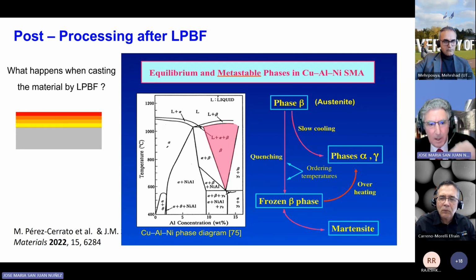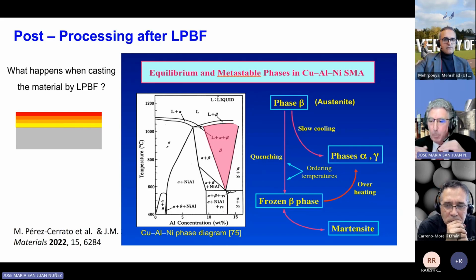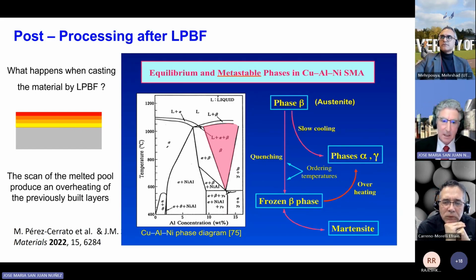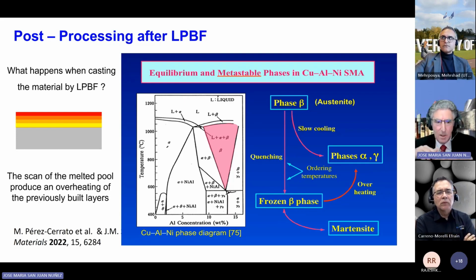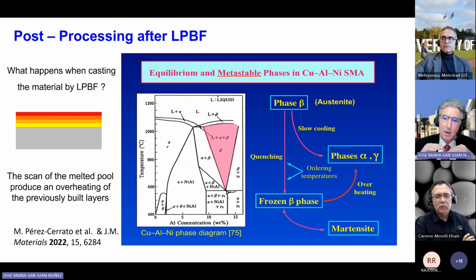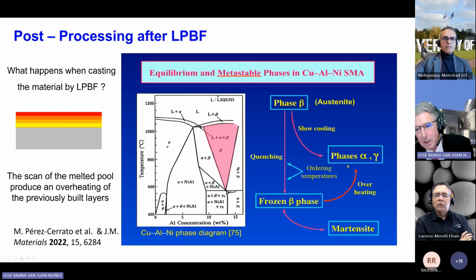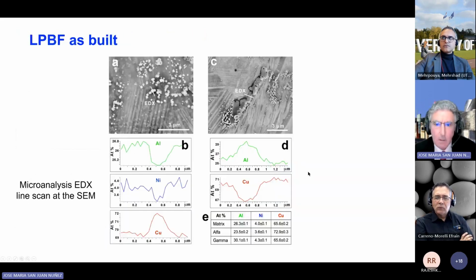Another overheating takes place below on the different layers. And this takes place again and again and again as we progress in the growing, in the building of the material. So systematically, the scan of the melted pool over the surface produces an overheating of the previously built layers. And this is the reason why we are overheating the frozen phase and then produce a precipitation of the equilibrium phases.